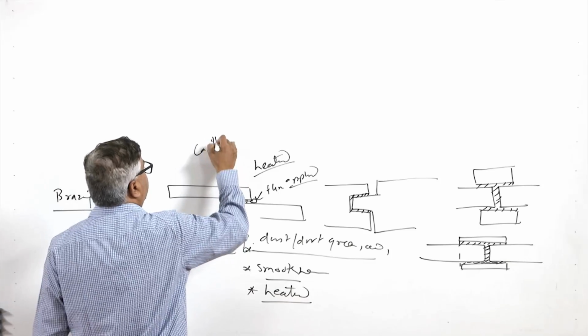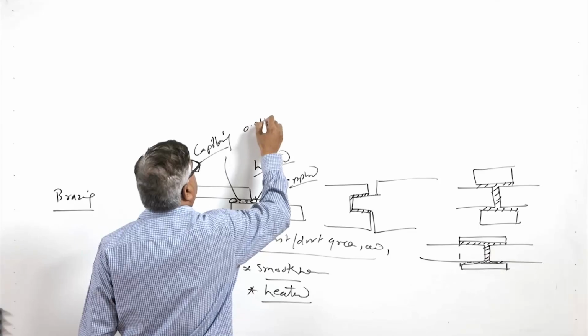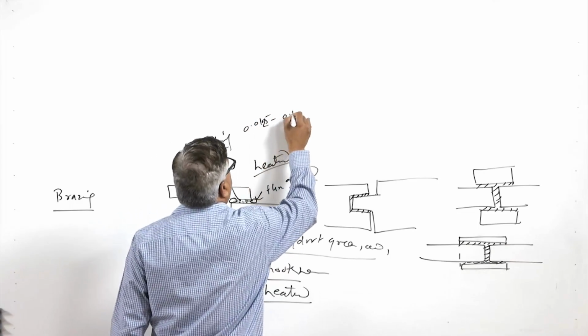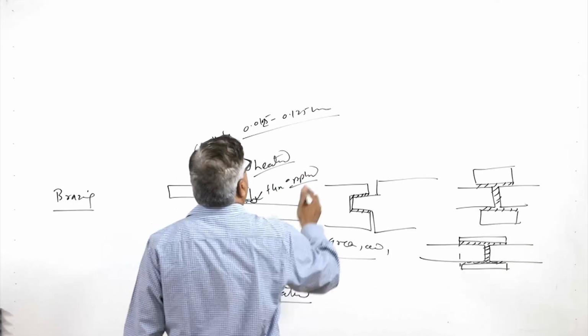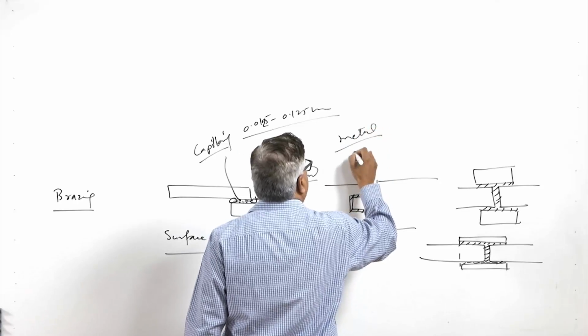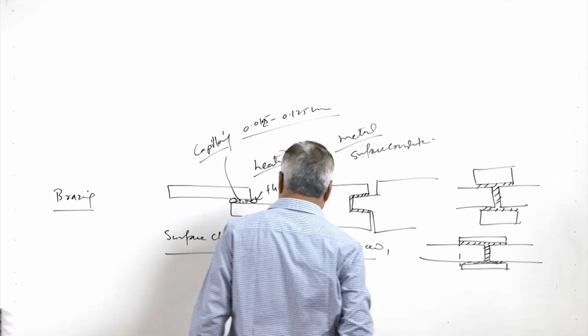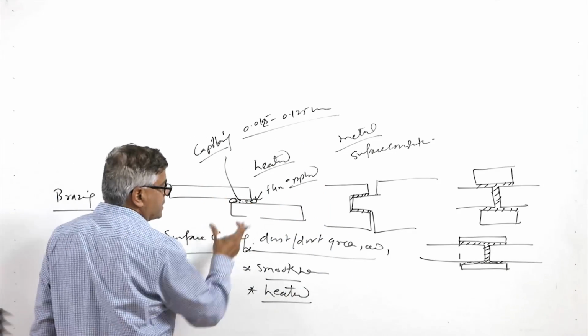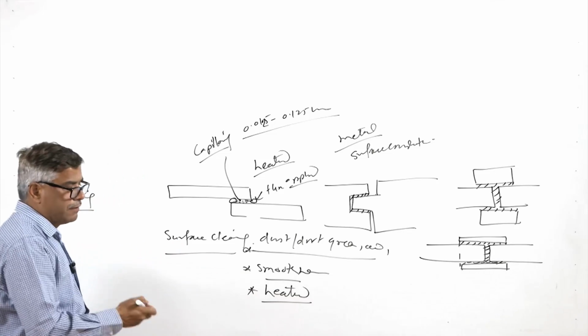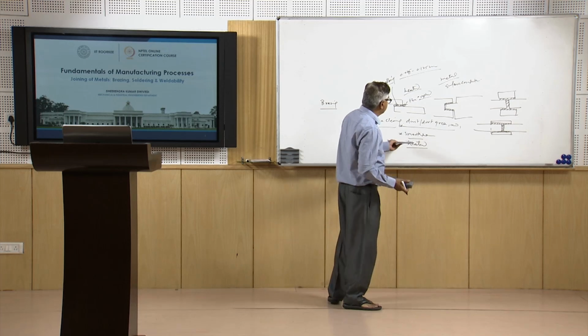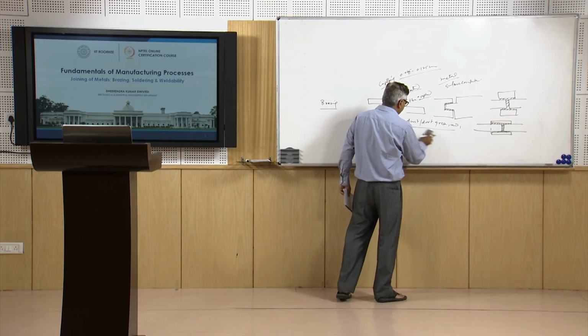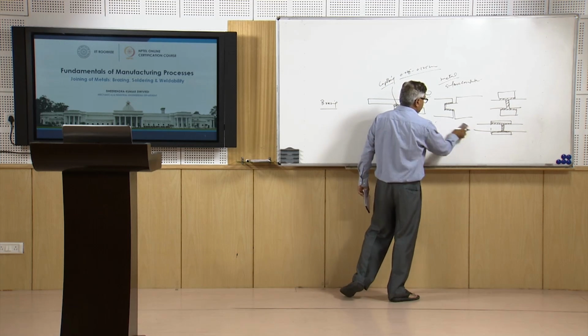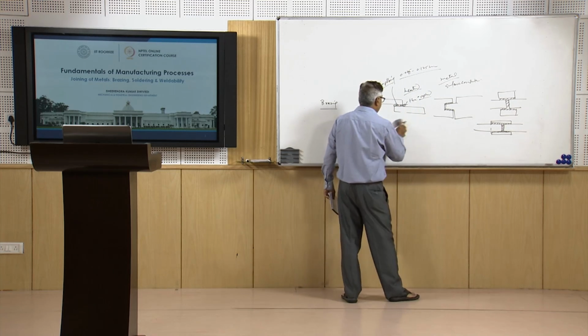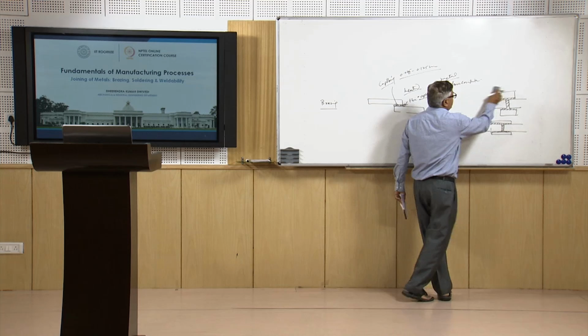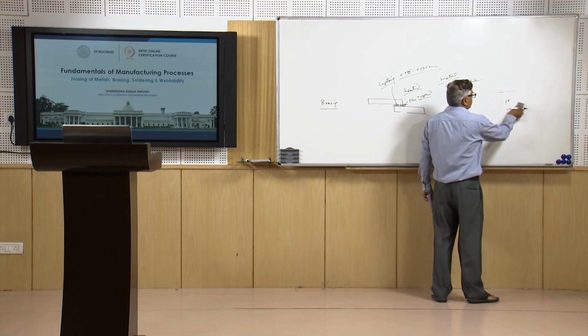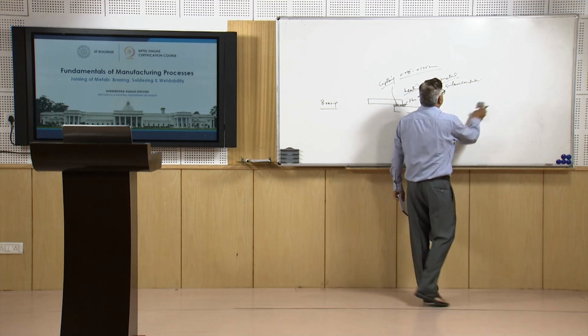For having this capillary effect, what is important is that the gap between the two is very closely maintained. A gap of 0.0125 to 0.125 mm is maintained, and this will depend upon the metal of the brazing alloy, the kind of surface conditions which exist at the surfaces, and the cleanliness. Since the flow is by capillary action, or distribution of the molten brazing metal between the faying surfaces, cleanliness, smoothness, and proper fluidity and wetting of the surface by the brazing material is important, and flux to some extent helps in removing the oxides and improving the fluidity of the brazing material, so that it can spread uniformly between the faying surfaces in order to form the joint. And after the solidification, the joint is produced.